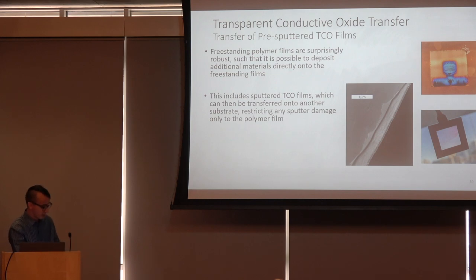You create this bilayer, which you can see in this SEM here. We have our TCO, ITO in this case, and then our polymer here. It's delaminating because it's a torn section of film. But you can pattern these films as shown here. That's our little ITO electrode on a freestanding film.